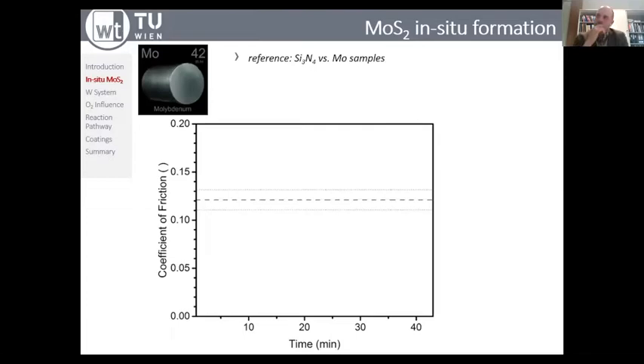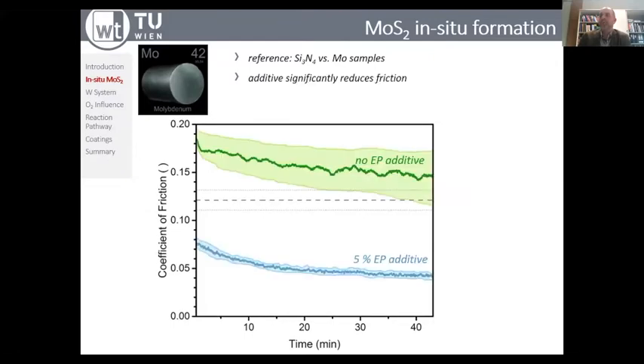We start with a very simple reference test. The reference is a bulk molybdenum sample, and as the counterbody we take a silicon nitride ceramic ball. We selected silicon nitride because it is much harder, inert, and not reactive to the molybdenum sample. And we start doing our test. You can see the coefficient of friction versus time. And then step by step, you are adding additive.